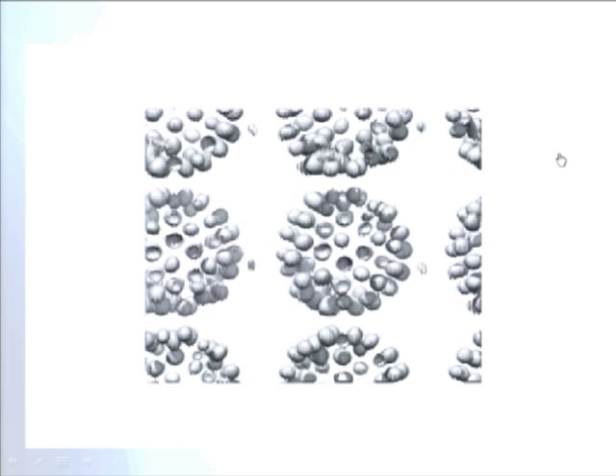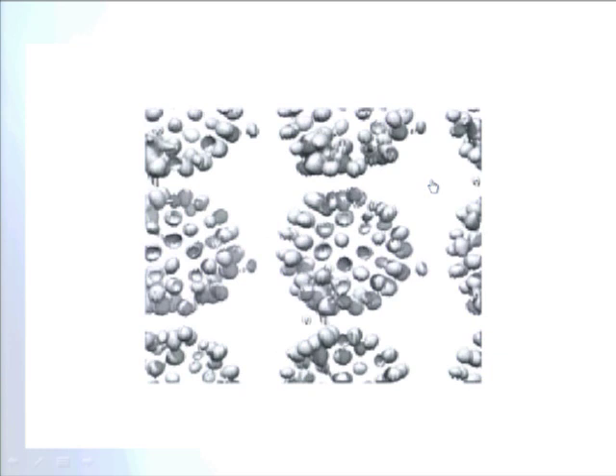This is what it looks like in reality — each frame is one electron density after one cycle of iteration. It seems that nothing is happening for many cycles as the method probes phase space, and then suddenly, at one moment, in five cycles or less, we get a solution. It's like throwing a stone in a valley: when the search comes close enough to the solution, it converges and just rolls down.